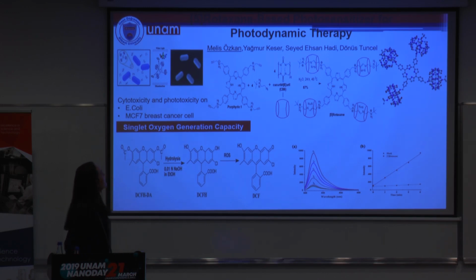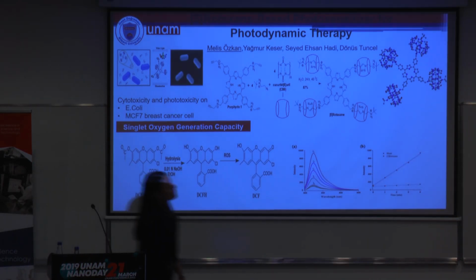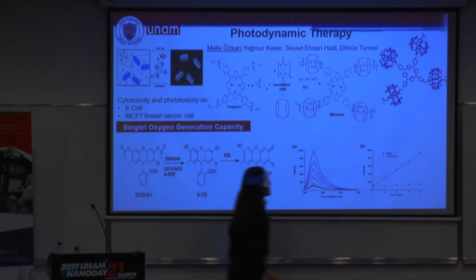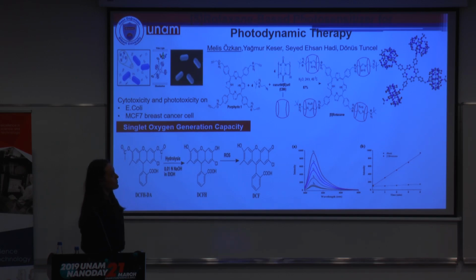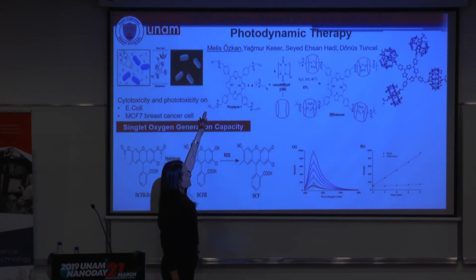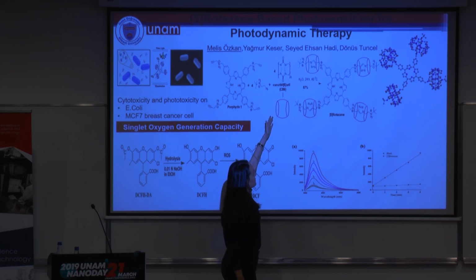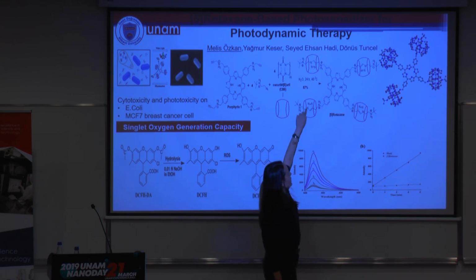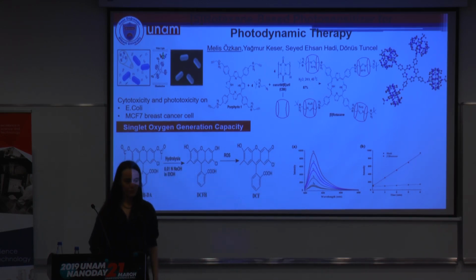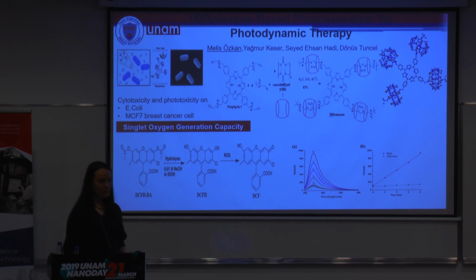In our project, we designed a [2]rotaxane-based photosensitizer for photodynamic therapy. Here, this is our drug, a supramolecular photosensitizer. We synthesize it through a catalytic self-threading reaction between alkyne-functionalized porphyrin and cucurbit[6]uril, CB6, which serves as a macrocycle and catalyst for that reaction, forming triazole groups, which results in a [2]rotaxane, our supramolecular photosensitizer. It has the ability to produce singlet oxygen very efficiently.